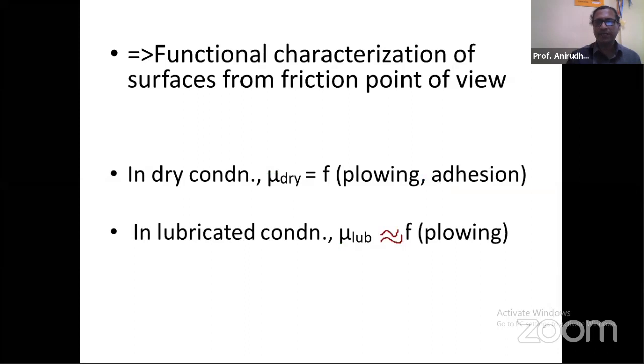So when these surfaces come into contact and are sliding against each other, when they form a tribo pair, if there is no intentionally added fluid or lubricant at the interface, then we would expect these metals, if they are two different metals, let's say, to come into contact. So there is adhesion. And then because of this roughness, when they are trying to slide against each other, the resistance to sliding, which we perceive and measure as friction, will have contributions both from stiction or adhesion and also due to ploughing. Now this ploughing is due to the interlocking of these asperities, and that is related to our roughness, while this adhesion is not so dependent on our roughness.